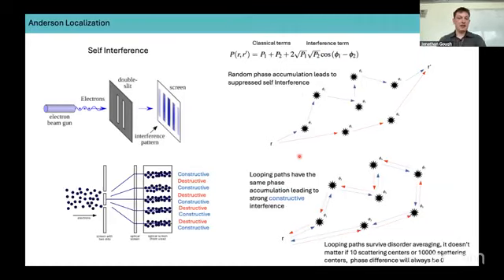However, if we now include this subset of paths, say clockwise and anti-clockwise around a closed loop, then you notice that the phases associated with the scattering events are exactly the same clockwise as they are for anti-clockwise. So the relative phase when these two paths intersect again at point R will be 0. So this cos term associated with self-interference will be maximized. So from this very simple toy model, you can see that these looping paths have an enhanced probability to occur.